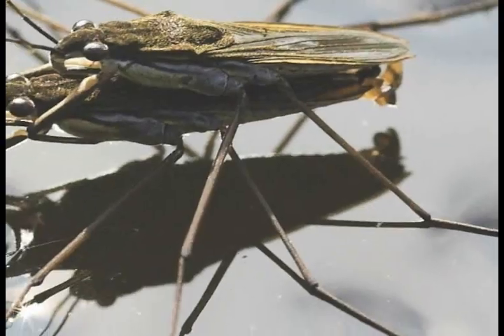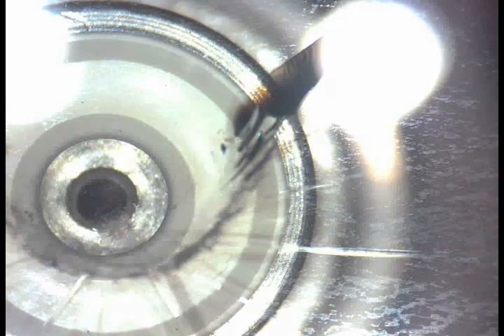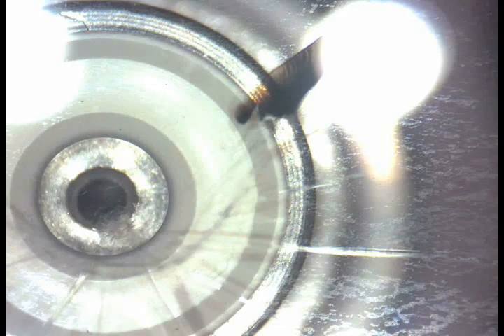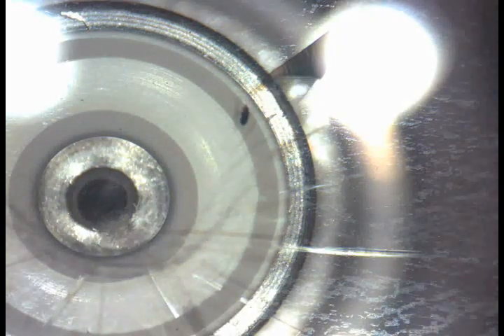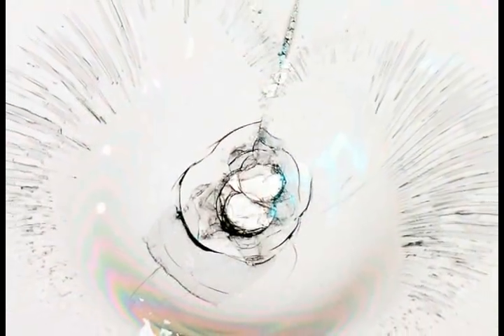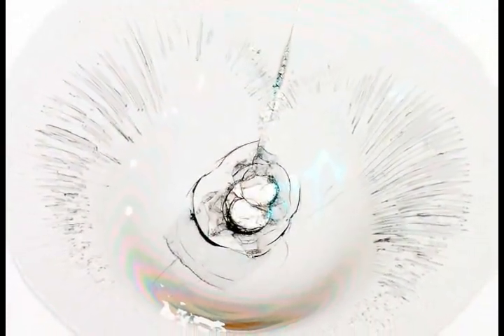Another aspect of resin selection is viscosity. Viscosity is a property of liquid that either resists or allows the liquid to flow. It is closely related to surface tension. For example, the thicker the resin, the harder it is for the resin to flow throughout the entire damage. Thicker viscosity resins, therefore, should be used in more open damages, such as a bullseye. Thinner viscosity resins flow more easily into damage. Therefore, thinner viscosity resins are good for the smaller spaces in tighter damage, such as a star break.